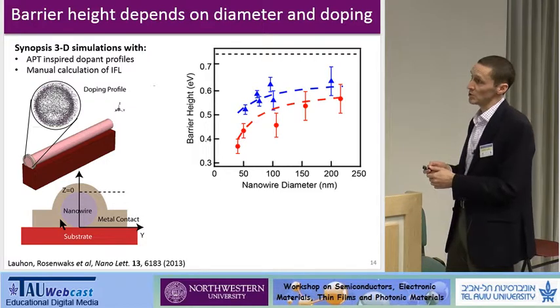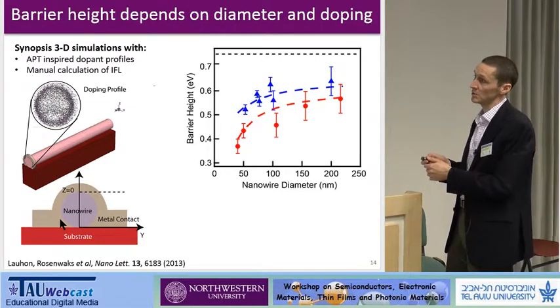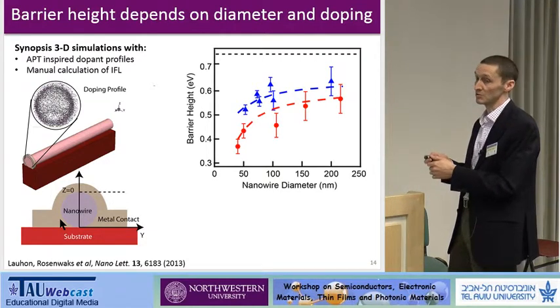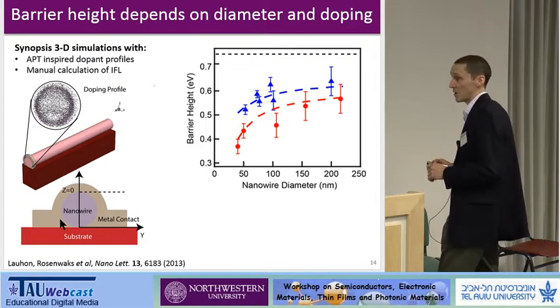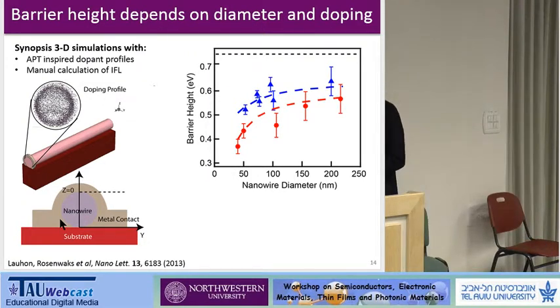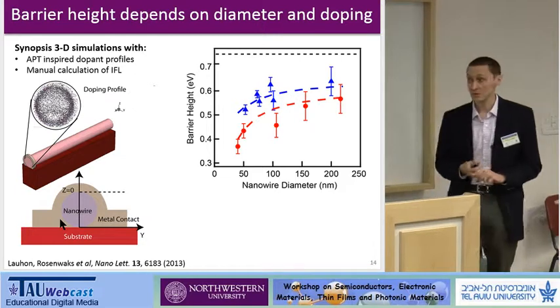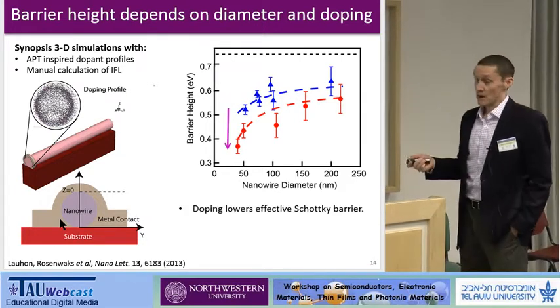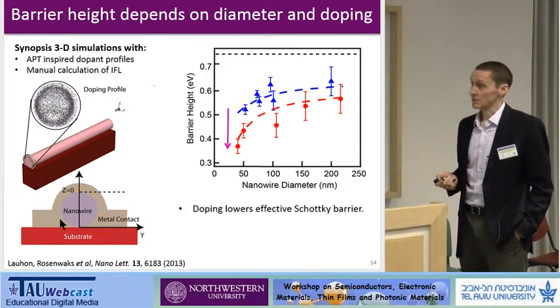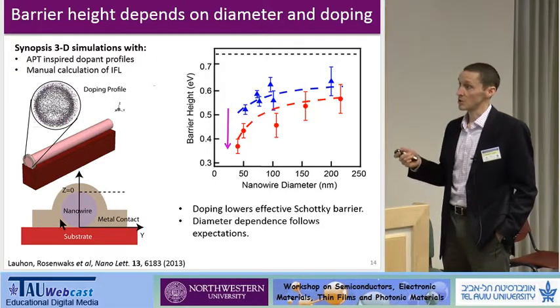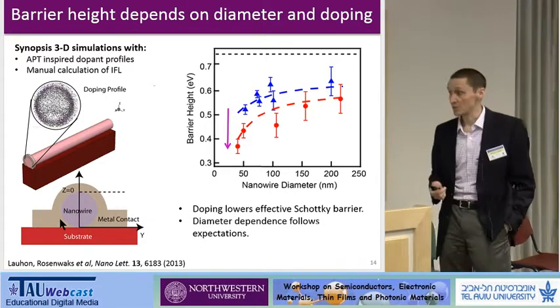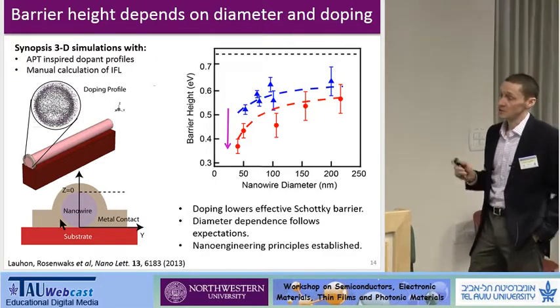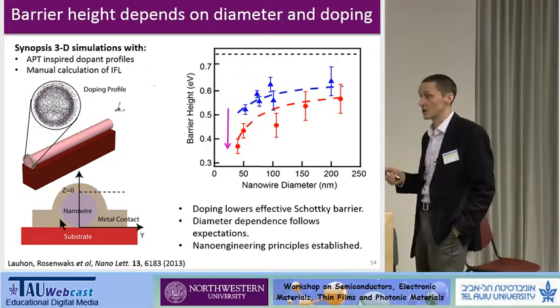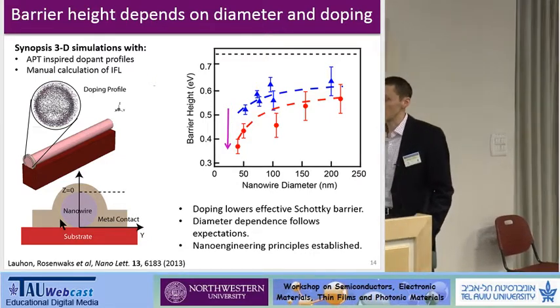And we found we could reproduce trends in the barrier height with diameter from left to right, and also with different doping levels by combining, again, atom probe, the Kelvin probe, and the internal photoemission measurements. So we find that, as expected, the doping lowers the effective Schottky barrier height. There's a strong diameter dependence that arises from geometry. And then, in addition, there are interface states whose occupation influences the barrier height.